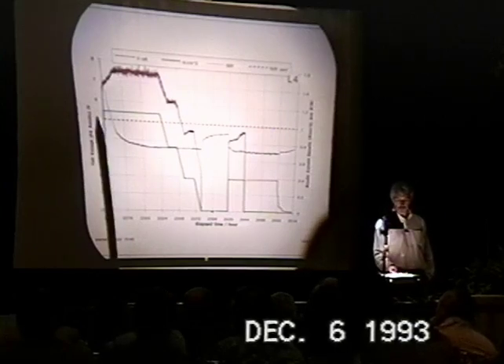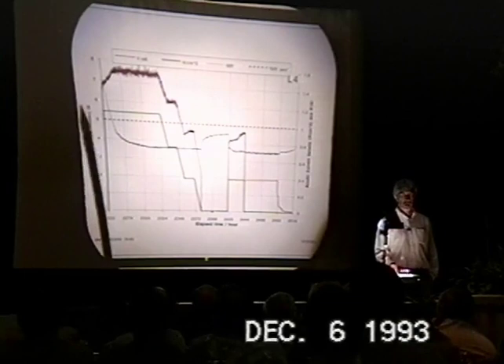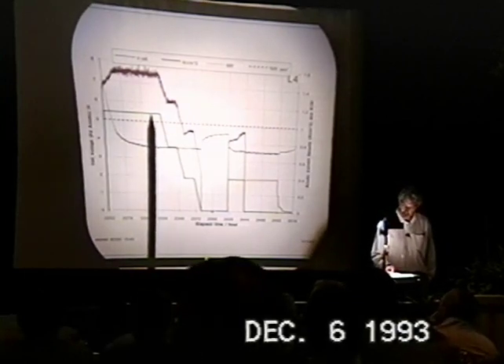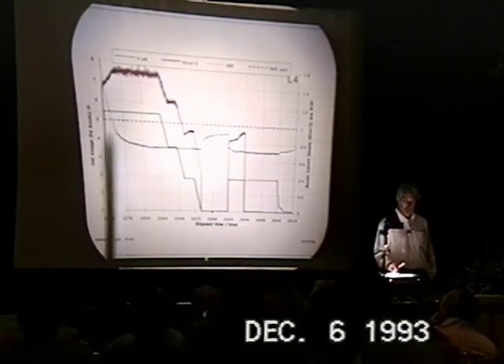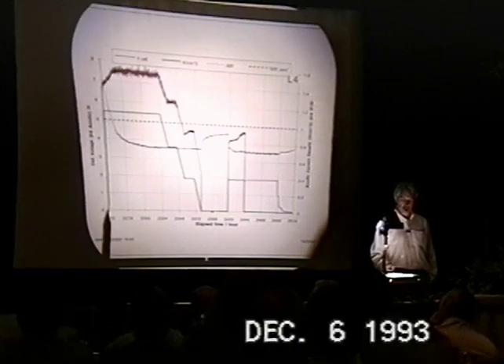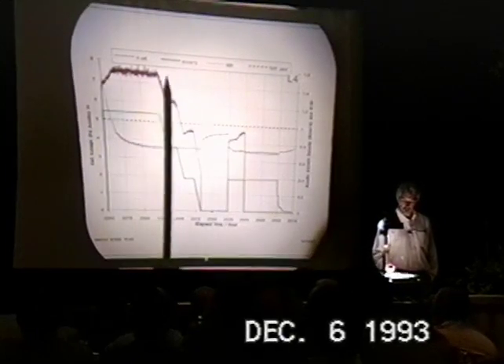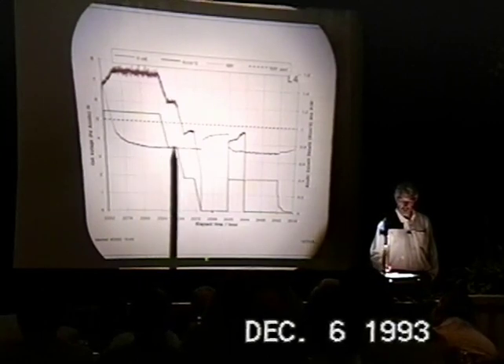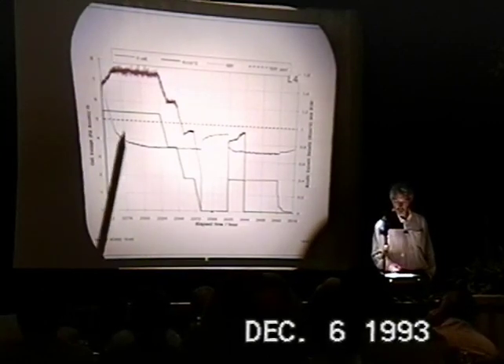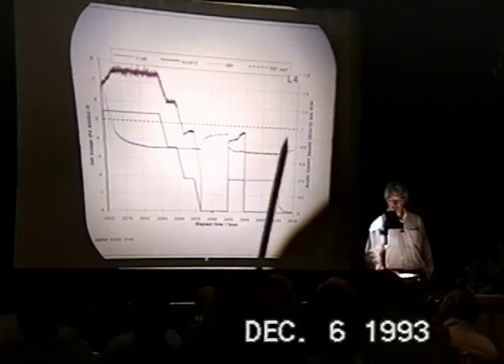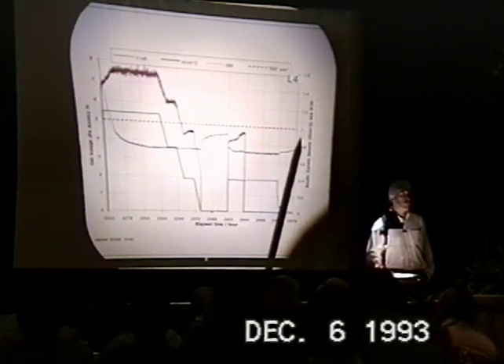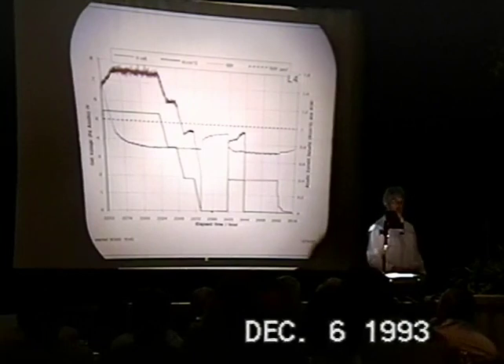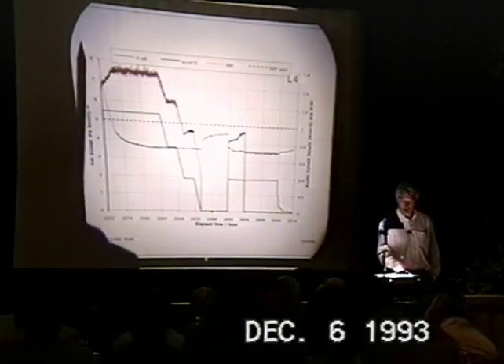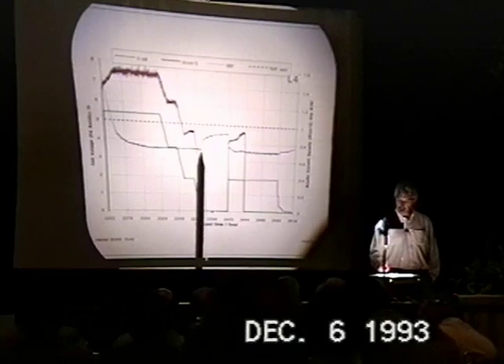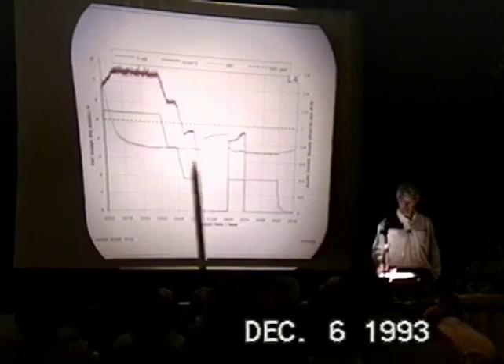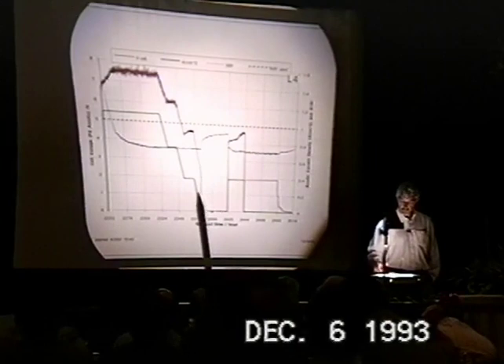In this case, we subjected this particular cathode to a very significant strip. It was being stripped at 1.1 amps per square centimeter, so that the cathode at this point was made anodic. The voltage follows this profile in response to this green profile of current density. The resistance ratio, instead of coming down and asymptotically approaching this value of 1, indicating that the resistance at the end is the same as the resistance at the beginning, goes through 1 down to a value of 0.7. This we didn't believe. We reversed the current,